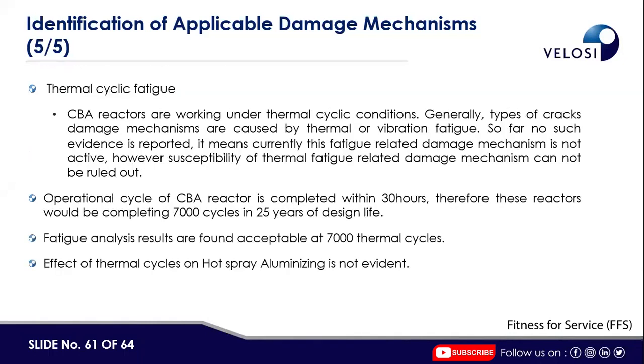Thermal cycling fatigue. CBA reactors are working under thermal cycle conditions. Generally, this type of crack damage mechanism is caused by thermal or vibration fatigue. So far, no such evidence is reported. It means currently this fatigue related damage mechanism is not active. However, the possibility of thermal fatigue related damage mechanism cannot be ruled out.